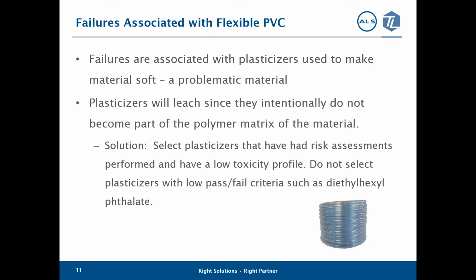Failures associated with flexible PVC are almost exclusively related to the plasticizers that are used to make the material soft. Plasticizers leach because they do not become part of the polymer matrix of the material. The solution for the manufacturer is to select plasticizers that have had risk assessments performed and have low toxicity profile. Plasticizers like diethylhexyl phthalate or DEHP have low pass-fail criteria, and they frequently result in failures. Using substances like DEHP as plasticizers should be avoided.